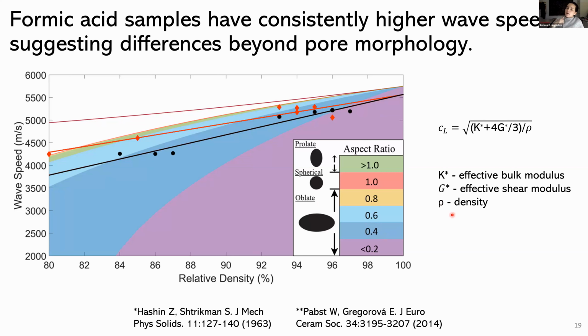We haven't completed X-ray CT on all of these samples, but we have no strong reason to believe that the formic acid pores are going to be significantly different in shape, although they might. So we think that another contributing factor, as you can see, like these are kind of shifted in that Y direction. Another contributing factor might be that the formic acid samples are actually forming stronger bonds between the grain boundaries.